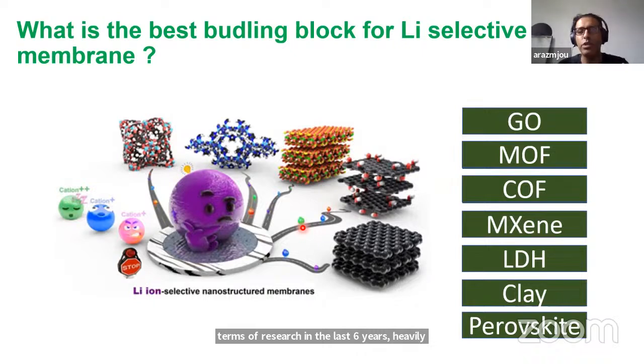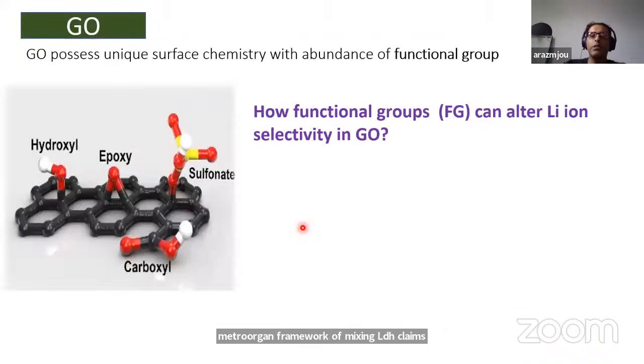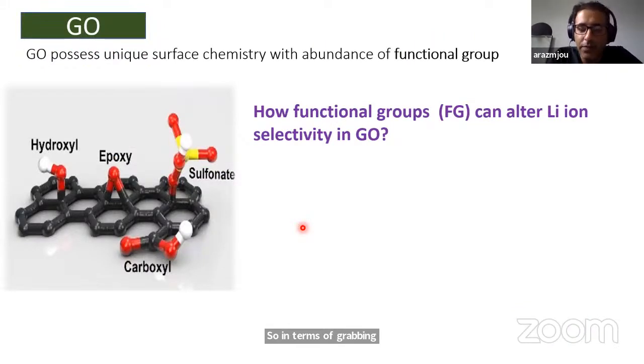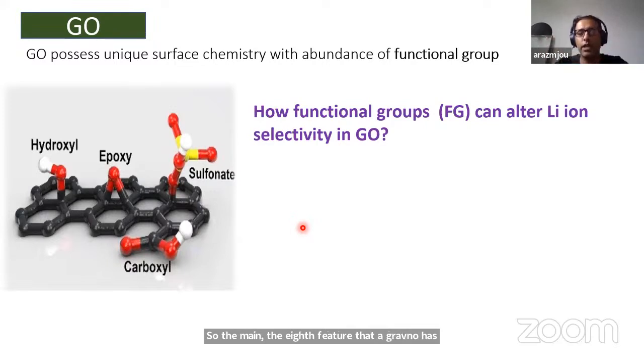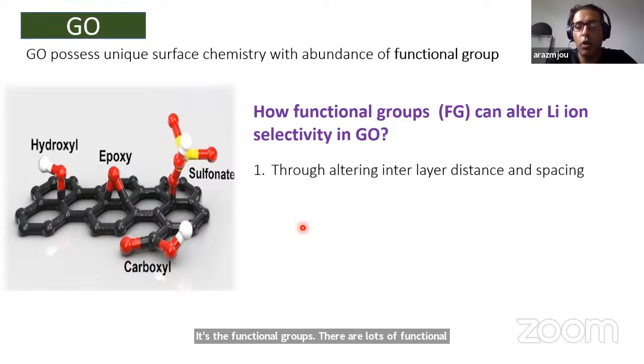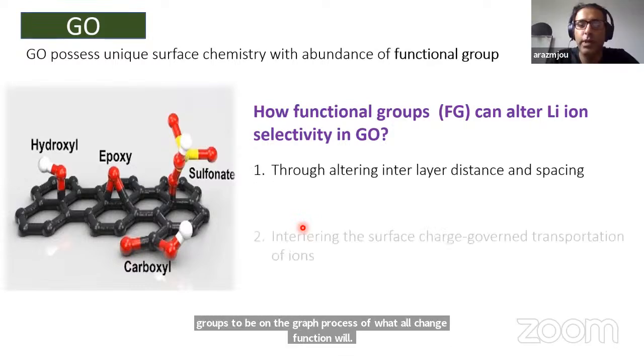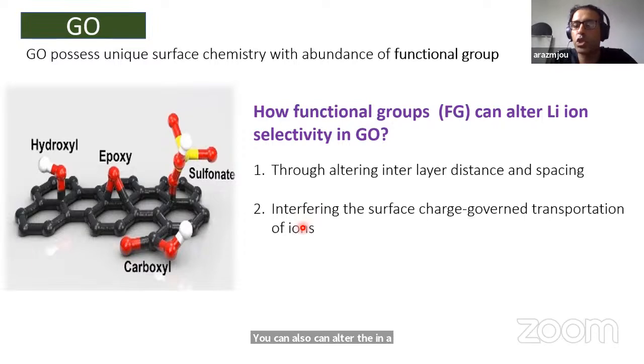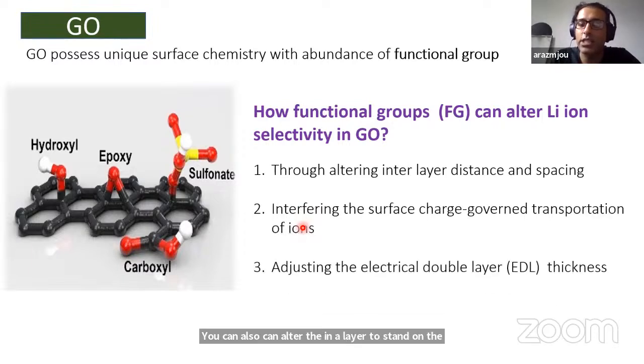So we have used a variety of building blocks: graphene oxide, metal organic framework, COF, MXene, LDH, clay processes. In terms of graphene oxide, the main feature that graphene oxide has is the functional groups. There are lots of functional groups on the graphene oxide. So by altering the functional group, you can alter the interlayer distance and the spacing, interfacing the surface charge governed transportation, and adjusting the electric double layer.